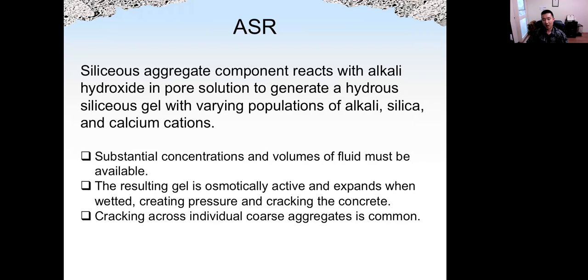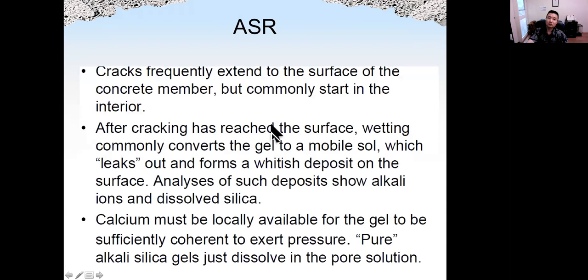Okay. And sometimes you see the cracking across aggregate. And the crack will extend to the surface of the concrete. And then when the crack reaches the surface, further expansion will convert the gel into a mobile sol, which will leak out and form the whitish deposit materials on the surface, as we see in the previous picture of the dams. And here it says calcium must be locally available for the gel to be sufficiently coherent to exert pressure. So we need calcium ions for the gel to apply the pressure. Pure alkali silica gel has very low viscosity, so it will just dissolve in the pore solution and cannot cause the cracking.